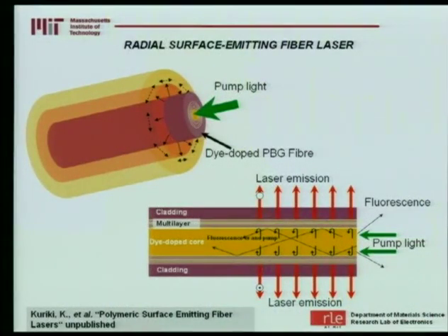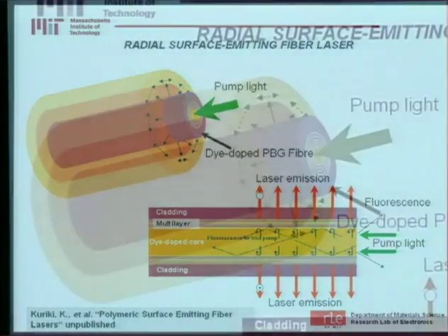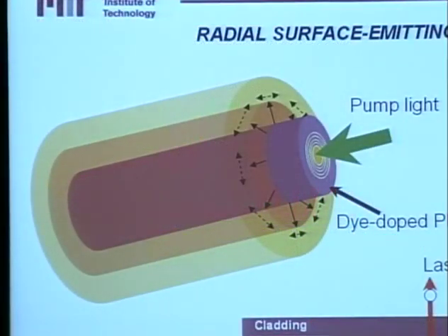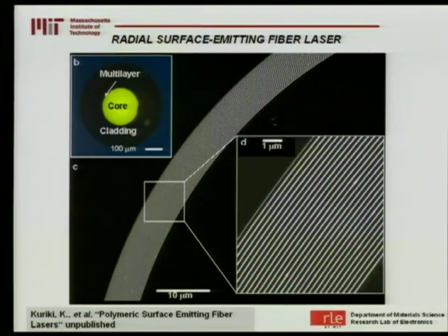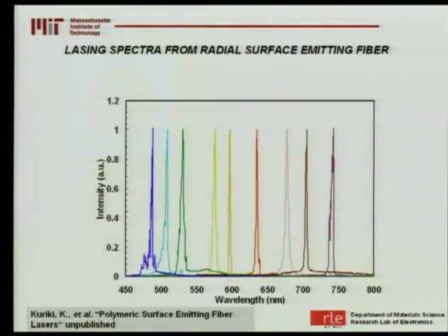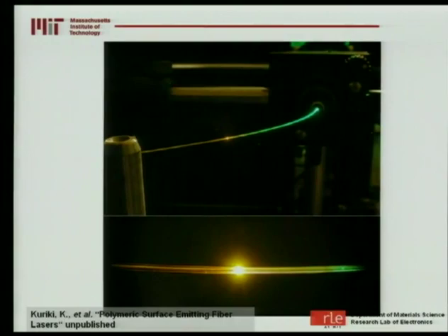In fact, if you consider what we have here, it is just an annular cavity, and in that sense, if you put a gain medium into this fiber, then you will have optical feedback, but the optical feedback is not going to be in the axial direction, but in the radial direction. And what you'll have here is a radial surface-emitting fiber. So here's what we do. We take a fiber. It has this mirror cavity. We fill it up with the gain medium, pump it, and get lasing lines. But the lasing lines are not occurring along the length of the fiber as normal fiber lasers would, but in the radial direction.